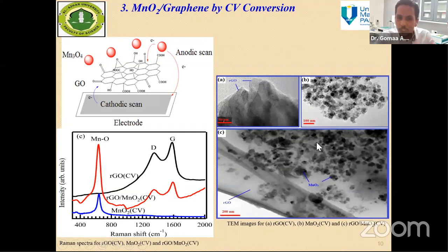of graphene sheets. As we can see here in the TEM image, this is pure graphene, showing the graphene nanosheets, and this is pure manganese oxide, showing the aggregated particles of manganese oxide, and the composite shows the manganese oxide nanoparticles distributed on the graphene sheets. In this case, we want to study the synergetic effect of these composites as supercapacitor electrodes.